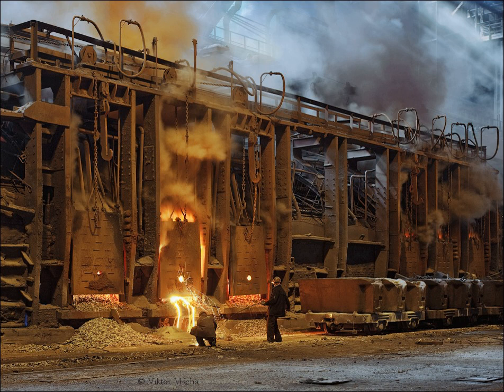The oxygen in iron oxide and other impurities decarburize the pig iron by burning excess carbon away, forming steel. To increase the oxygen contents of the heat, iron ore can be added. The process is far slower than that of the Bessemer converter and thus easier to control and sample for quality assessment. Preparing a heat usually takes eight to eight and a half hours. As the process is slow, it is not necessary to burn all the carbon away as in the Bessemer process, but the process can be terminated at any given point when the desired carbon content has been achieved.